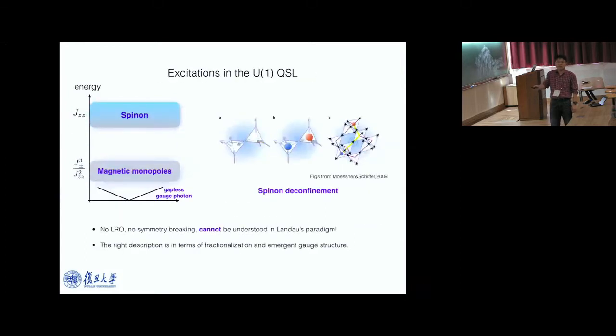So deconfinement naturally leads to fractionalization, but fractionalization can be manifested explicitly in the symmetry. Deconfinement and symmetry are two different concepts, but if you impose symmetry on the deconfinement or fractionalization, these fractionalized particles will carry fractional quantum number of the symmetry, and this has strong experimental consequences. This is very similar to the fractional quantum Hall effect, where if you do not have global U(1) charge conservation, the Laughlin quasiparticle does not have fractional charge. But as you impose global charge conservation, your Laughlin quasiparticle can carry fractional charge. You can remove that global charge conservation by putting a superconductor on top of the fractional quantum Hall state, but the topological order is still preserved, while the fractional charge disappears.